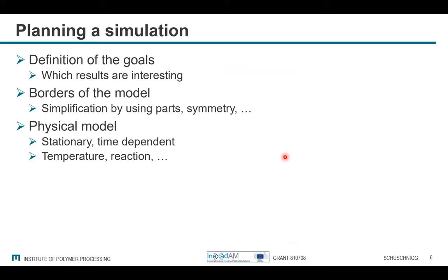What are the borders of the model? What simplifications can I make? Do I have to simulate the whole part, or can I just use a small part of it, because there the changes will be the most critical? For example, I have done many simulations for underwater pelletizing, and the whole inlet was mostly not interesting, because 99% of the pressure loss was at the die tips. And so very often I just simulated the die tips, because the pressure loss was the most important thing.